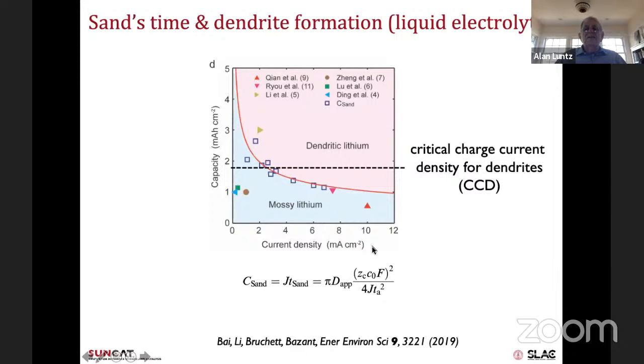And it turns out that where this actually forms is when the concentration of lithium at the surface gets small enough that the rate of the reaction is dominated by lithium diffusion to the surface. So you only get diffusion limited aggregation instead of a reaction that's dominated by the electrochemical reaction of the electrode. And it turns out this depends heavily on the concentration of the electrolyte and on what's called the anion transference ratio, which is that when you apply a field, you pull the anions away from the anode, and they pull the lithium ions with them. So that can deplete the concentration as well.